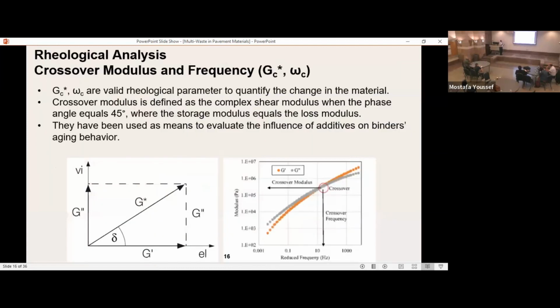Again, synergy. So the first and the most important test, in my opinion, would be looking at the fundamental change in the rheology of the asphalt. I think I saw this graph in two presentations ago for the complex modulus. In a viscoelastic material, you have your elastic component and your viscous component contributing to your overall modulus. What controls the contribution is really the phase angle between them. If you know that at the angle 45, the elastic component, G prime, and the viscous component, G double prime, are equal.